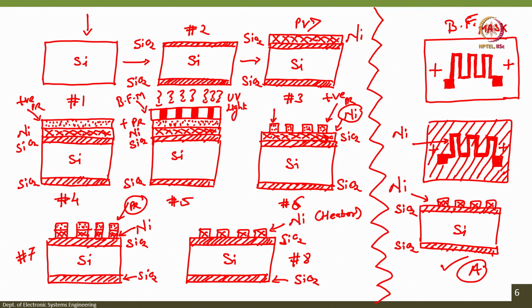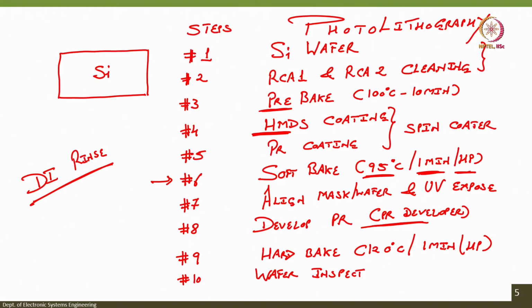When you dip the wafer in nickel etchant, what will happen? Wherever photoresist is protecting the nickel will stay intact, in the remaining area nickel will get etched. After that, you dip this wafer in acetone, which is wafer number 7, right, and when you do that, the photoresist will get stripped off to form your nickel micro heater or nickel heater, right. These are the steps for photolithography. These are the exact steps that we have talked about here, right.